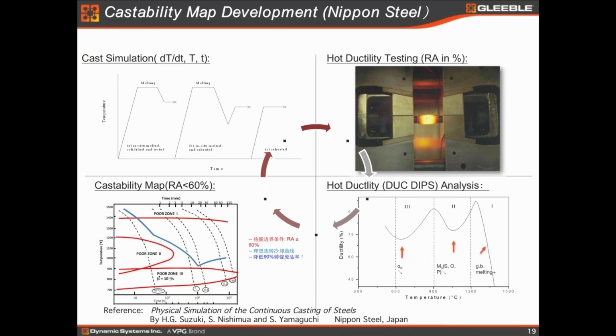We have bad elements like phosphorus, oxygen, sulfur, all these. You need to make all these elements as minimal as possible. That's why we have so much clean steel technology, like RH and these kinds of vacuum degassing, all these technologies to make the steel purer and cleaner. That way you can make the ductility bigger and better to avoid all this cracking you see.